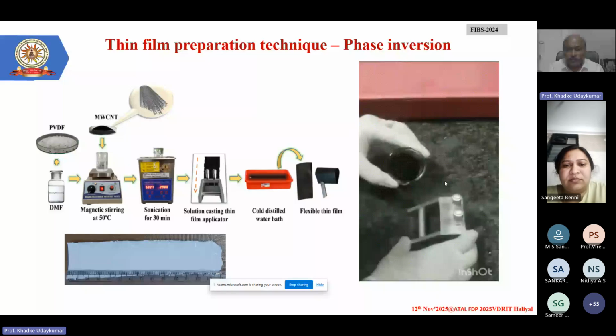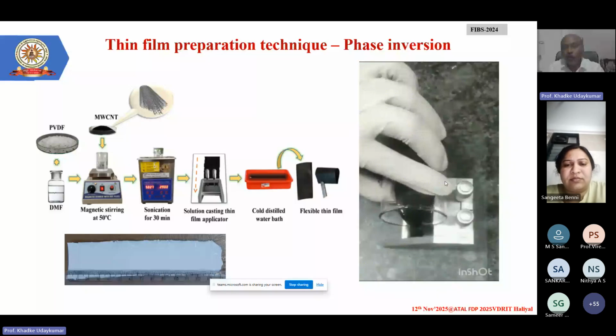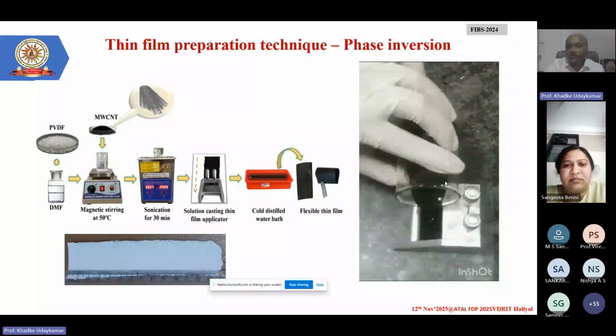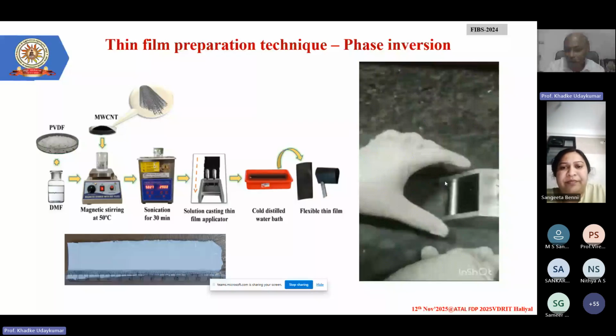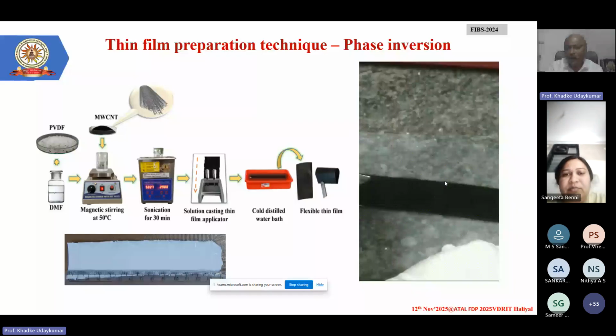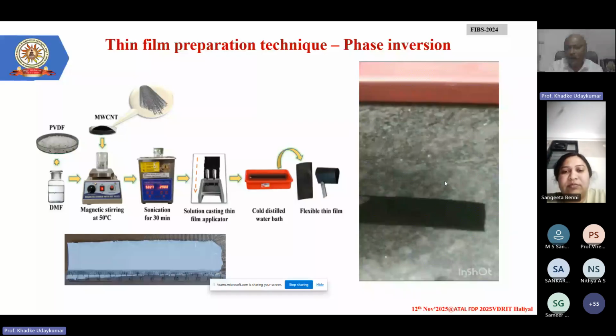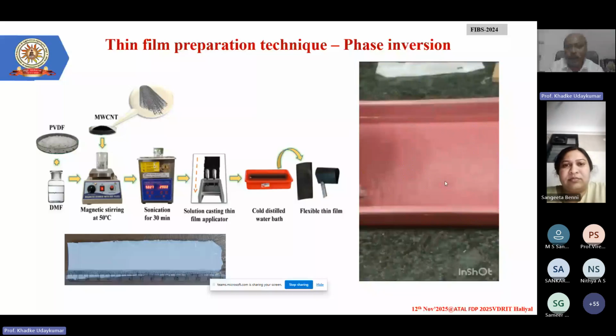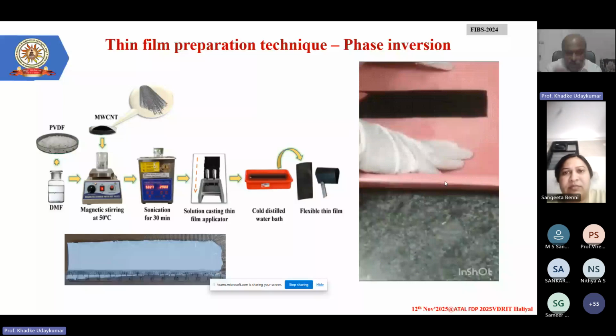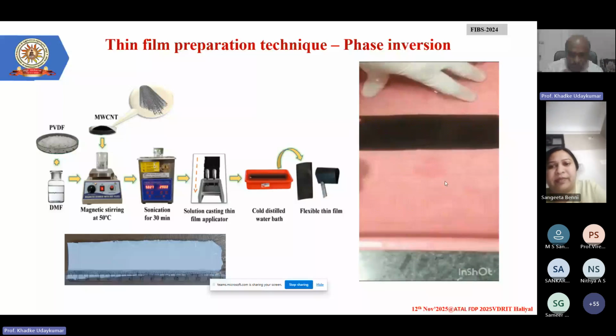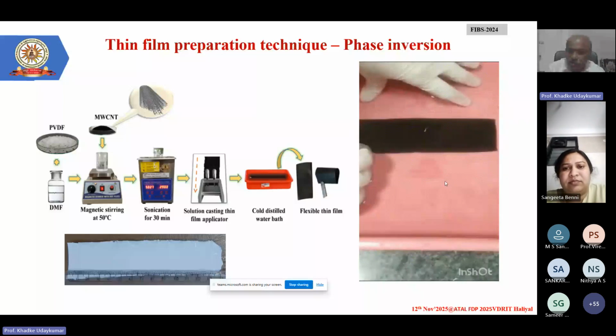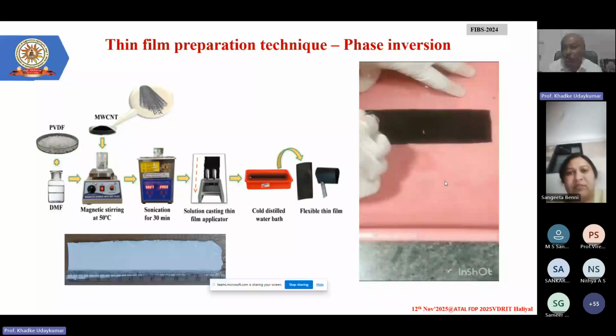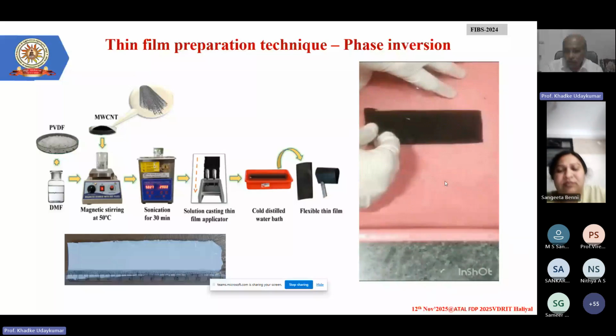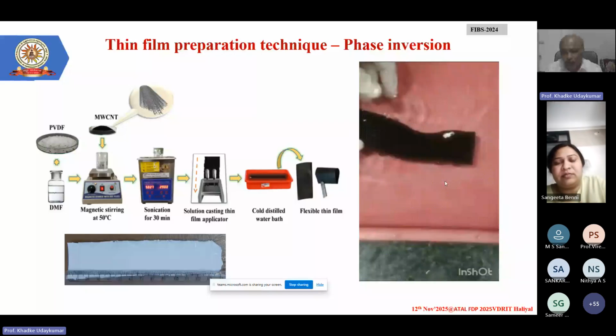Now, for the film, we have taken utmost care to have uniformity on the surface. At the same time, the density of the material is uniform, and this is a technique that has been developed in my lab. Probably I can say that we are able to prepare a thin film of the order of around 250 to 300 micron size, that too self-supporting. Some people say that these are not thin films, these are thick films. Okay, but anything in terms of micron size can be considered a thin film, and you can see how beautifully the films are coming out. So even the dimension, that area, will also be very large.